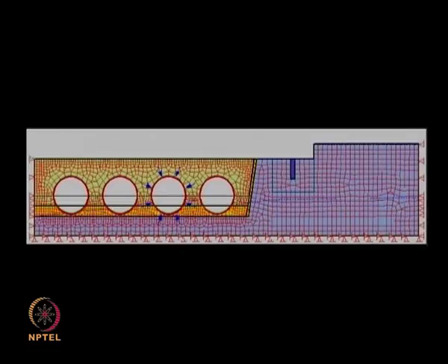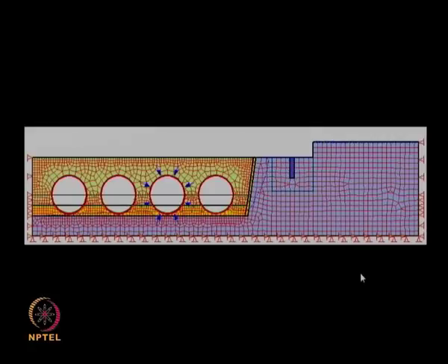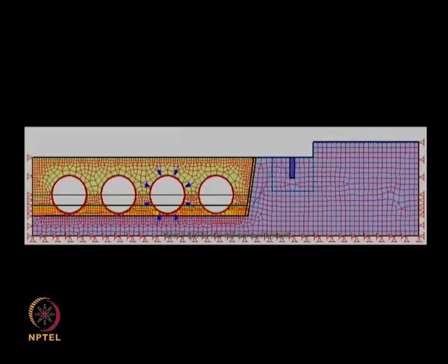In this case a remedial measure is in place, wherein a filter layer has been placed at this level. This is the application of soil mechanics, as in earthen dams: if a filter layer is induced, it prevents the water table and maintains the water table right at the bottom of the pipe, which reduces the external pressure and prevents the pipe from losing the support from the soil. In the earlier case, the stresses became very high, and it led to a very high amount of non-uniform stresses, which led to the failure. This is the situation where the water table is drained and diverted with a so-called drainage layer, which is placed to suit the site condition.